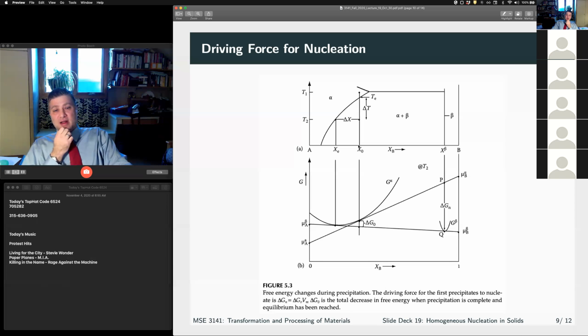If I start with an alloy of this composition, X naught, and I come down from the single phase region into the two phase region, I can draw my Gibbs free energy curves for both alpha and beta, and I know that I can reduce my overall free energy of the system by the common tangent construction by phase separating into alpha of this composition here and beta of this composition here. And my net reduction in free energy is delta G naught. That's my overall driving force to separate out the phase.